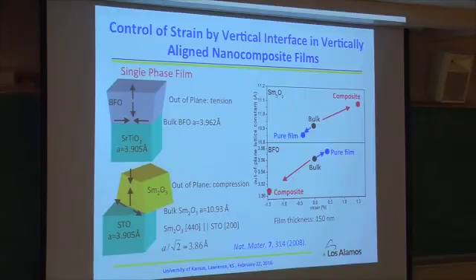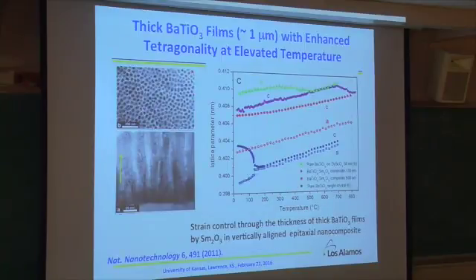However, when you do this pillar structure, you see you totally switch this. Okay. Why is that? Well, it's really the vertical interface that controls your strain, not the lateral interface anymore. So actually, that's a very, very powerful way you can really control the crystal structure and thereby the functionality. Another thing I mentioned earlier, you can go to very, very thick film. Typically, the critical film thickness depends on the lattice mismatch. It's anywhere from probably tens of nanometers to a couple hundred nanometers, that kind of range. It really depends on the materials we are talking about. But here we are talking about even going to 1 micron, still strained.